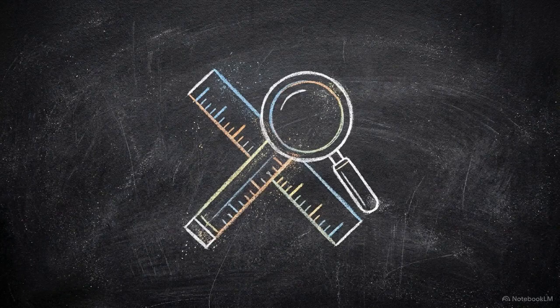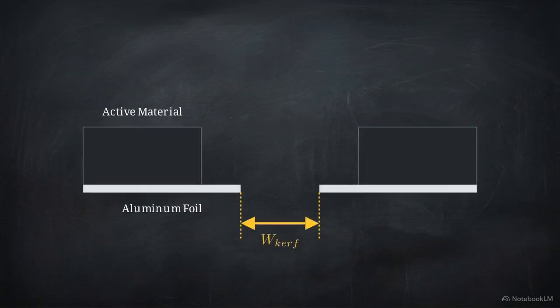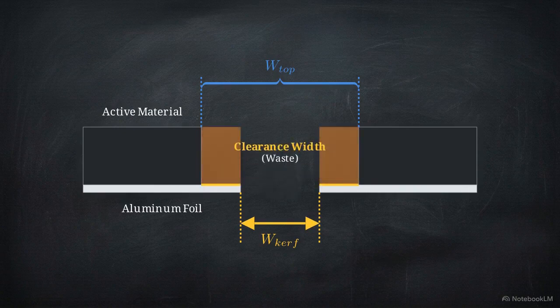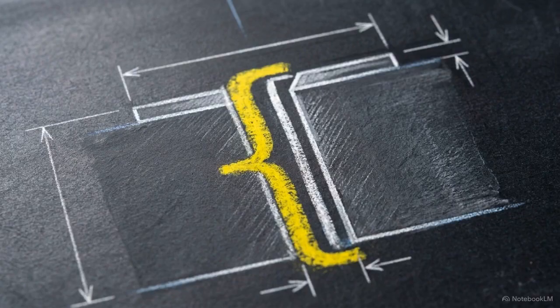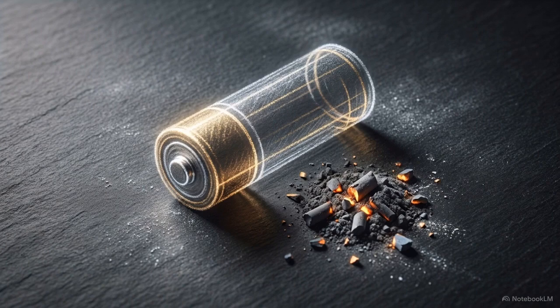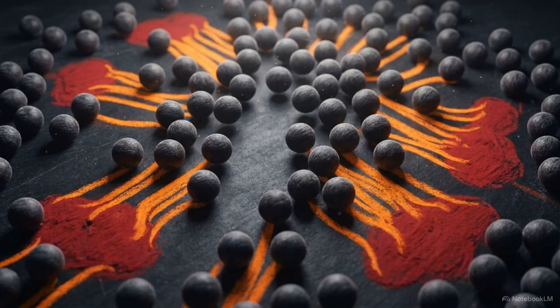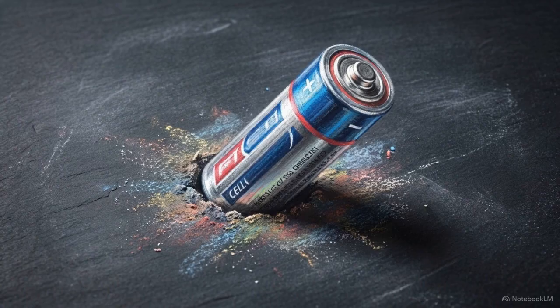We evaluate the quality of the cut using two specific metrics. The first is the kerf width, the physical gap where the aluminum current collector is entirely removed by the laser. The second is the top width, the wider zone bordering the kerf where heat has stripped away the active material, leaving the underlying foil intact. The physical difference between these two measurements is the clearance width. It dictates the exact amount of wasted active material along the cut edge. The physical configuration of the electrode dictates how heat moves through it. Controlling that thermal physics minimizes material loss, which ultimately determines the battery's true capacity.